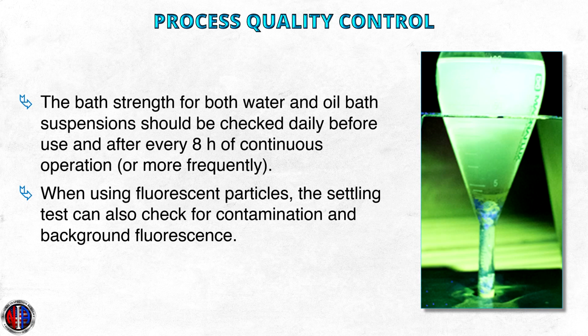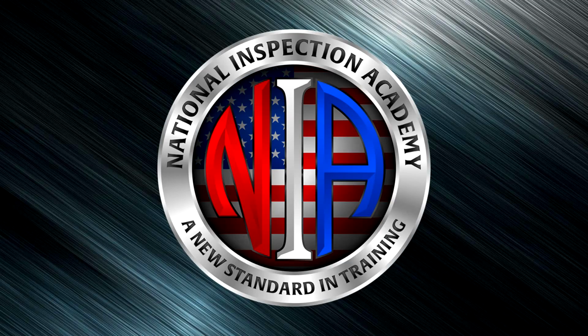When using fluorescent particles, the settling test can also check for background fluorescence. Under UVA light, only the particle layer should fluoresce. Fluorescence in the liquid indicates bath breakdown, with fluorescent pigmentation being stripped from the magnetic particles or fine magnetic particles remaining suspended in the media. And that concludes this lesson.